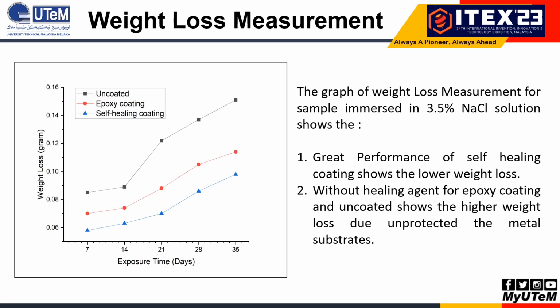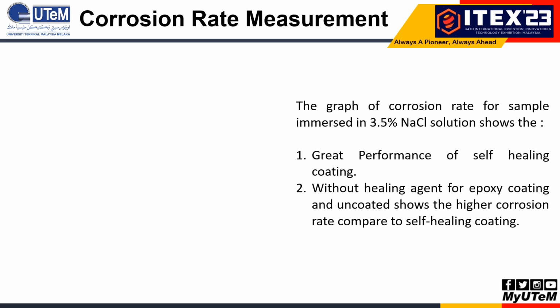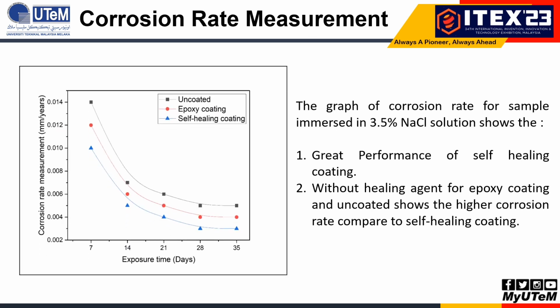For the corrosion rate measurement, the graph of the corrosion rate for the samples immersed in 3.5 weight percent sodium chloride during exposure times of 7, 14, 21, 28 and 35 days shows the great performance of the self-healing coating. Without the healing agent, the epoxy coating and uncoated show a higher corrosion rate compared to the self-healing coating itself.